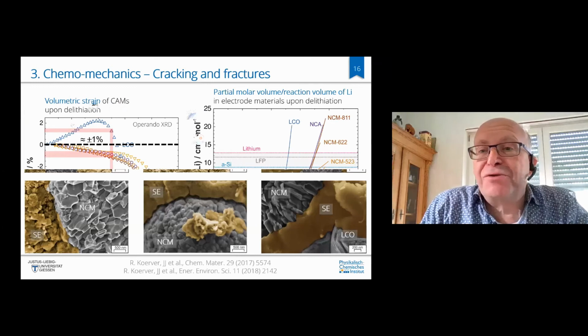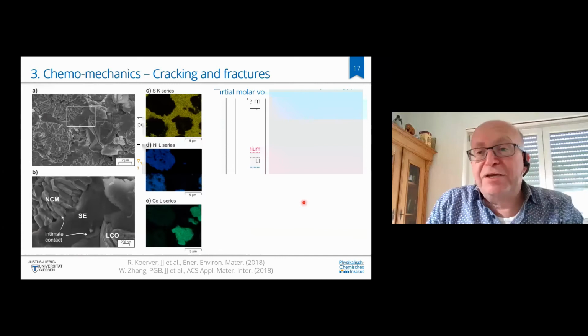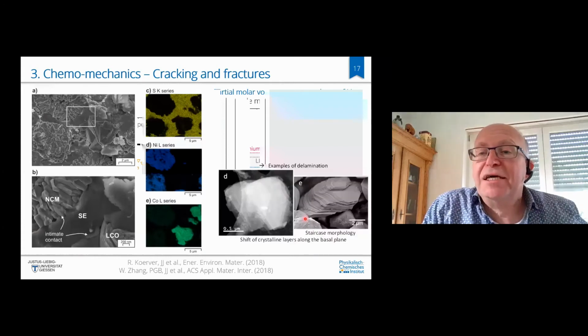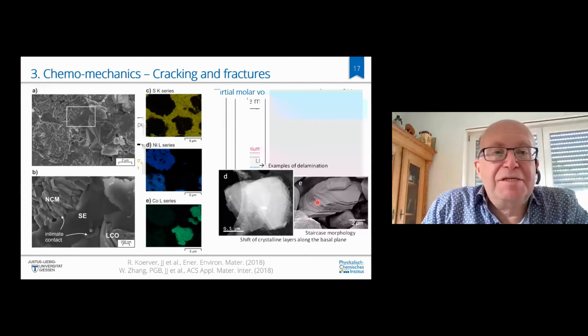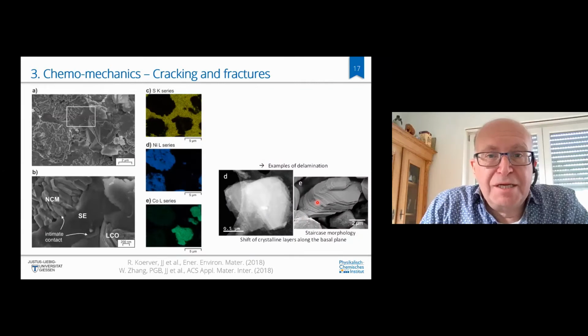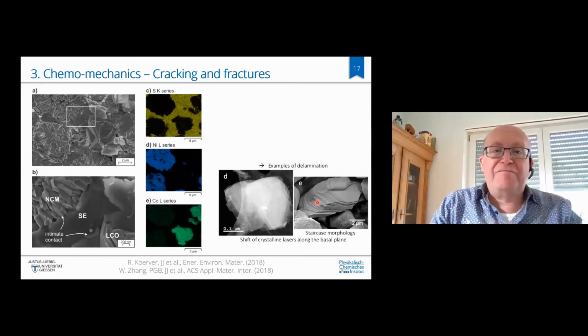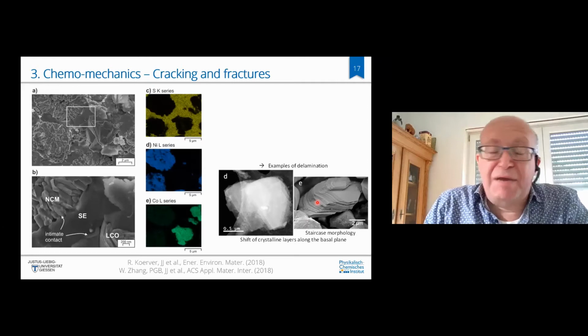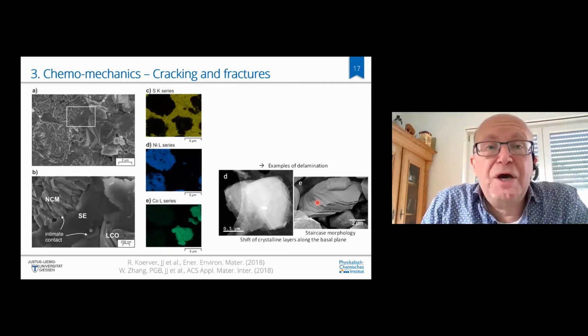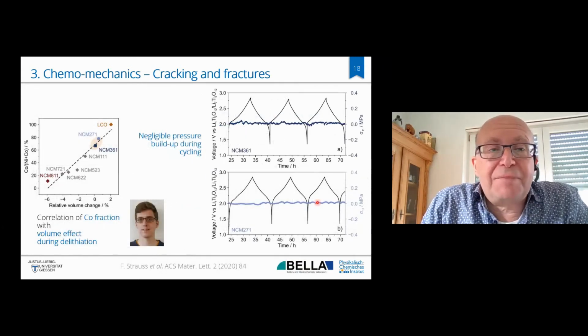Now, what Raimund did, he showed that by mechanical blending, by taking shrinking and expanding NCM and LCO particles, you can mitigate that problem. However, internally, of course, locally, there's still lots of strain. And for example, you see here that this LCO particle really has been strongly strained and deformed under the impact of local strain in these solid state cathode composites. So I think there are probably only two real solutions. One is you need any kind of mechanical buffer layer around the particles. Maybe the coating has to be a buffer layer, maybe a polymer, or you need cathode particles that do not show volume changes. And this is shown here.